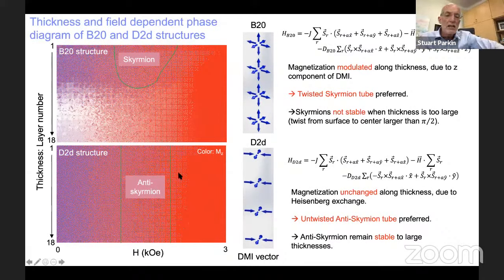Whereas for the anti-skyrmion in the D2d symmetry Heusler compound, there's no dependence on the thickness of the lamella in the absence of dipole fields. These calculations do not include long-range magnetic dipole fields. So there is a big contrast, and that's related to the symmetry of this crystal structure, which is reflected in the symmetry of this exchange vector. In the B20 systems, which are cubic, this means that it will stabilize a twisted magnetic structure in all three directions, and effectively wants to stabilize spherical objects.